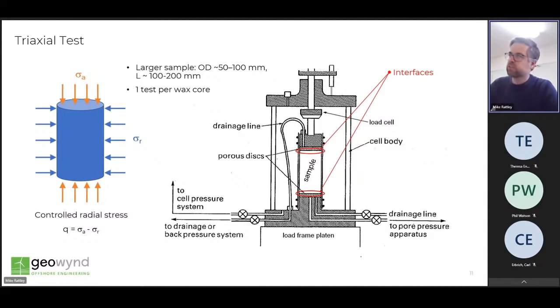Adjustment of the deviatoric stress acting on the specimen in a drained state via a loading ram allows an anisotropic stress state to be achieved, and anisotropy of a stress condition can also impact on cyclic response. Shear stresses are then induced in the specimen in the undrained condition through additional deviatoric load and with the drainage lines closed, allowing excess pore water pressure to develop in the specimen during shear.